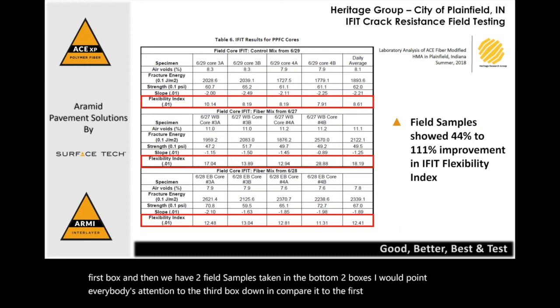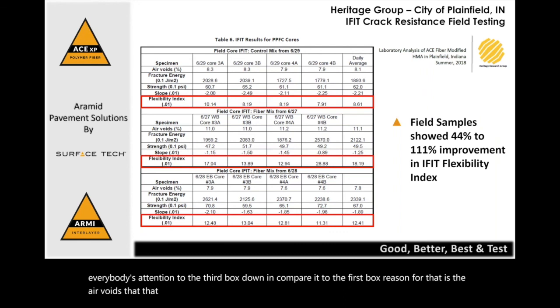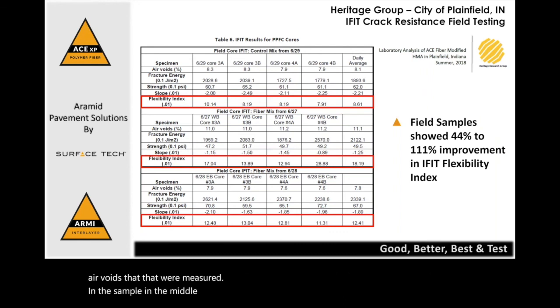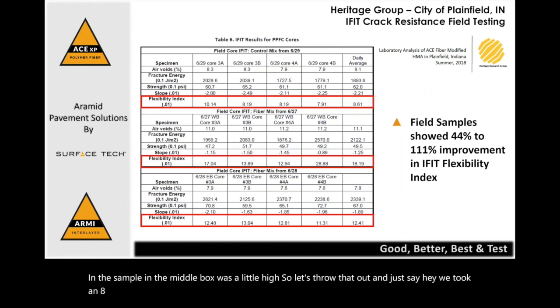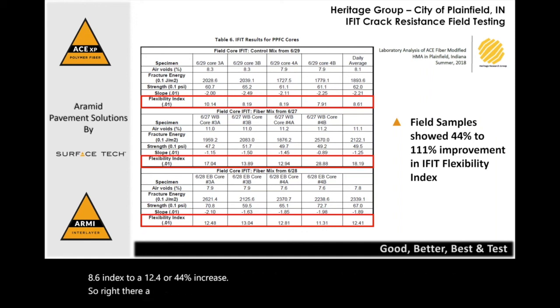The reason for that is the air voids that were measured in the sample in the middle box was a little high. So let's throw that out and just say, hey, we took an 8.6 index to a 12.4 or a 44% increase. So right there, a single dose went up 44%. Go ahead, Phil.